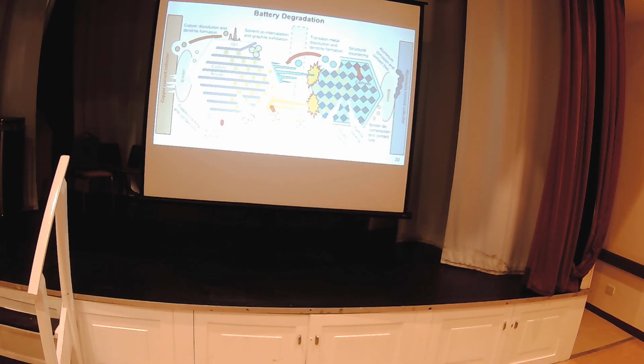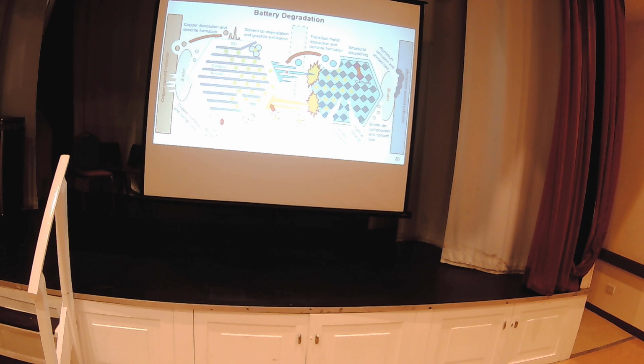So coming back to the battery degradation picture. A little bit of what happens is, this is lithium plating, it has a needle-like structure. When we can't extract lithium completely, it could be any issue, maybe the lithium was not good, or when we charge there's some circuit issue, that forms lithium plating. It doesn't happen quickly, but it requires certain time, or the same hazard happens again and again, and it will tear up the separator, which is a barrier between cathode and anode, and touch the cathode, which will cause short circuit or explosion of batteries.